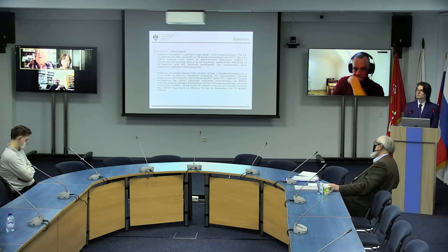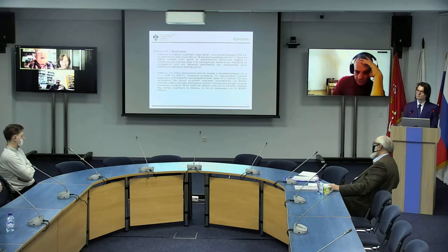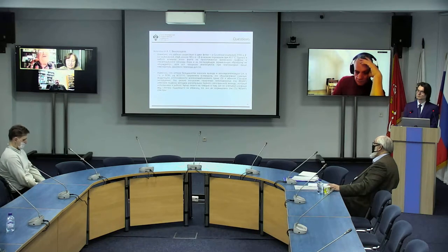Third point, in the literature review on page 12, when describing the crystalline structure of graphene, you say this type of structure is defined by sp2 hybridization of atomic orbitals, and two orbitals are associated with the formation of sigma bonds, and the remaining orbital participates in pi bond formation. That's an incorrect expression, because we see the formation of three equivalent hybrid sigma orbitals that provide for triangular coordination of carbon atoms in graphene, and the pi bond is achieved due to the fourth one, 2pz.